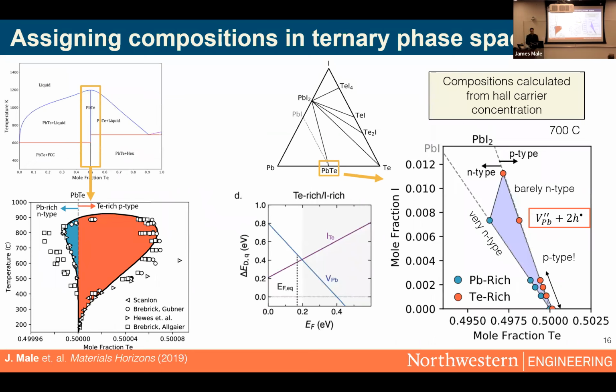Whereas before I used this binary phase diagram as a useful tool to guide my defect engineering, in this case we're actually adding a third element, so we need to look at a ternary phase diagram to make this same sort of useful tool. So I used my measured carrier concentrations along with some DFT defect calculations, which were done by Anush Goyal, which show that all of the compensation of my dopants is due to lead vacancies. Knowing that, I can reliably calculate the amount of lead vacancies I have in each of my samples and recreate a ternary phase diagram with actual compositions. So now you see in ternary phase space, the same sort of phase width becomes quite important, similar to what we have in binary phase space.